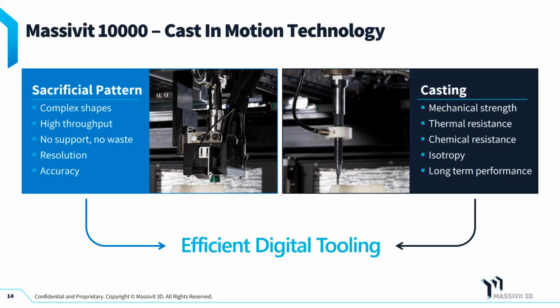So great technology, big hollow parts, and that's where the light bulb went on with our founders, who said, why don't we use that to cast a strong material, a 2-part epoxy? That's what you're seeing happening on the right. We're printing about 8 to 10, 12 layers, depending on the size of the part, of the shell material, the UV cured material. Then it stops, that head moves out of the way, and we fill that gap, that shell, with a 2-part epoxy. It has great mechanical properties, but one of the key problems in 3D printing is that the layers make for a weak part in the Z direction. By pouring a 2-part epoxy that has an open time of about 20 to 30 minutes, all those pour intervals blend together and we create an isotropic mold, which you can't do in 3D printing any other way.